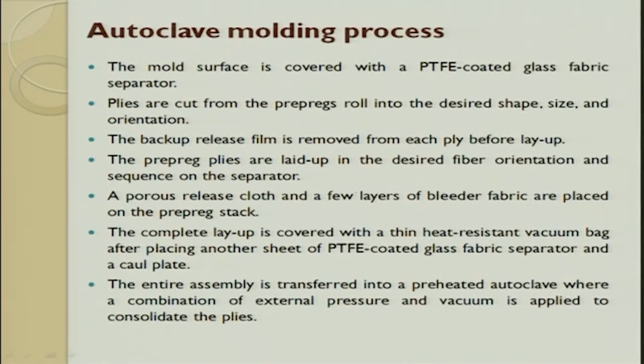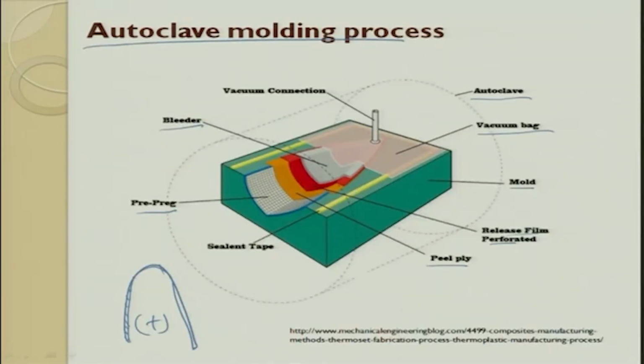So in the molding process, what happens? I will go to the figure which I have already dealt with. You put the prepreg. Before the prepreg, you put a small coating at the bottom, a releasing agent. Then you put the prepreg. After that you put a peel ply. Then you put a perforated releasing film. Then you put a bleeder, so excess resin can travel up to here and get absorbed. On top of it you put a vacuum bag, and this vacuum bag is sealed such that this portion is completely consolidated. So this is what is dealt with in the process.